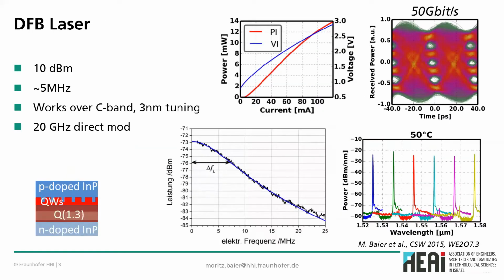Of course, our technology being an indium phosphide technology, we have a direct bandgap semiconductor, so it's very easy for us to achieve optical gain and therefore lasers on chip. So on this slide, you see the performance of our DFB laser summarized. It's a complex coupled DFB laser. It delivers around 10 dBm of output power on chip. Its wavelength can be set anywhere in the C-band by design, and you can even thermally tune it by around 3 nanometers. And because it's a really small footprint device, you can actually modulate it up to 20 gigahertz. In the upper right corner, you see a PAM4 eye diagram operating the device at 50 gigabit per second, so 25 gigabaud.